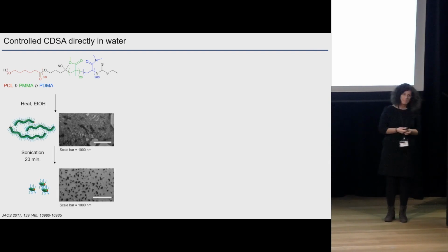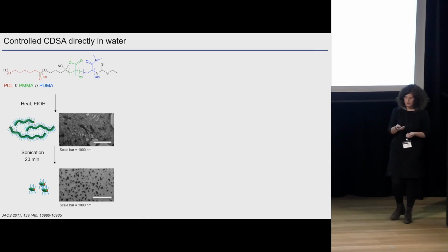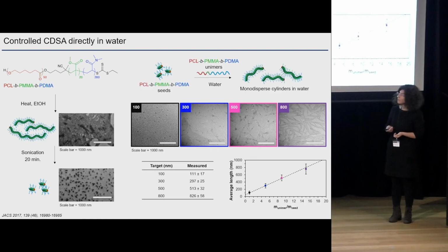These can be self-assembled using the same conditions as I showed before. So you heat it in ethanol, then you sonicate to get your seeds. And differently from before, you can actually transfer the seeds into water, and then you can grow the nanoparticle by adding sequential amounts of polymer. As you can see in this graph here, there is a very linear relationship between the amount of polymer we add and the size that we reach. So we get excellent control of nanoparticle size.